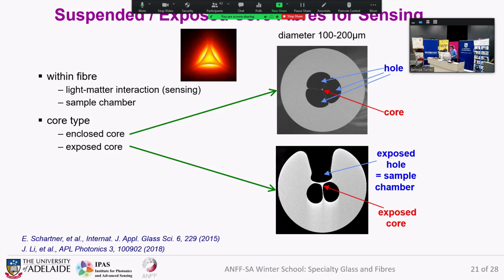Part of the light guided along the glass core is situated outside of the glass in the air holes, and if you fill the air holes, the light can interact with what's in the air holes, which is used for sensing. So we achieve light-matter overlap, and the air holes allow this access to the light but also act as the sample chamber.